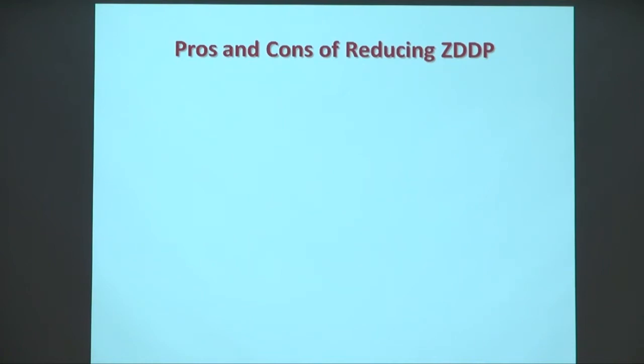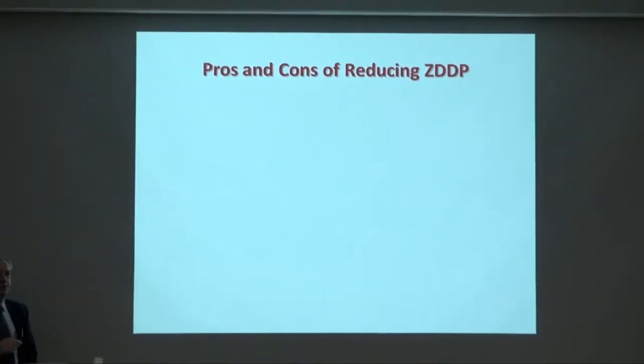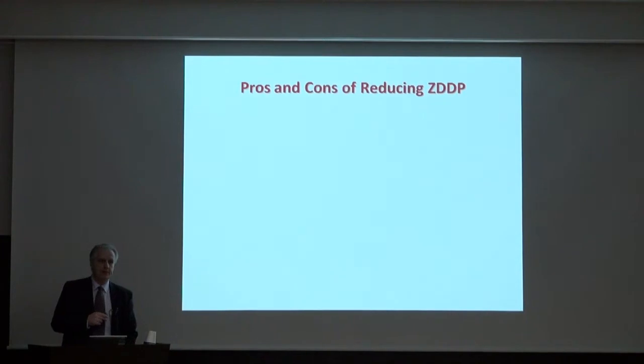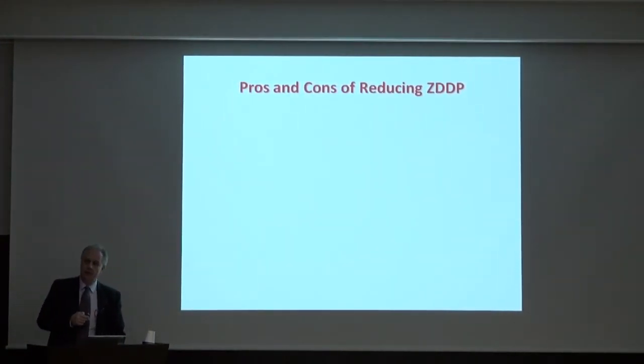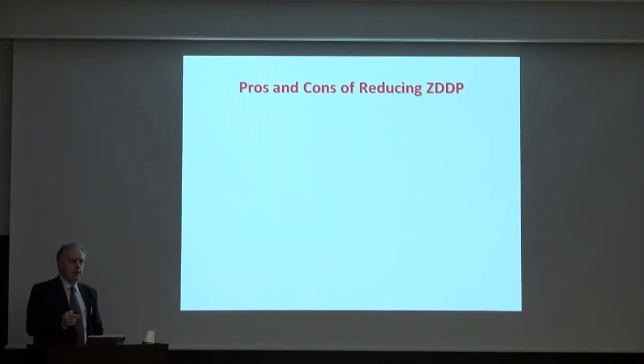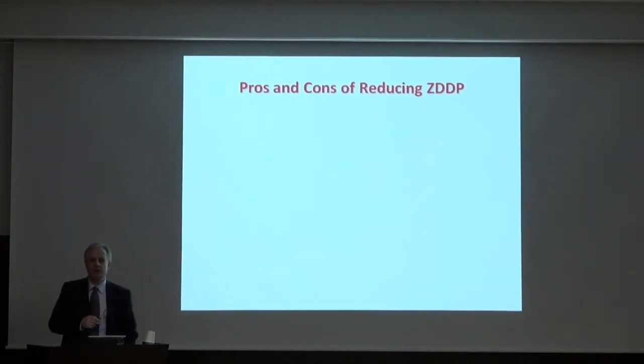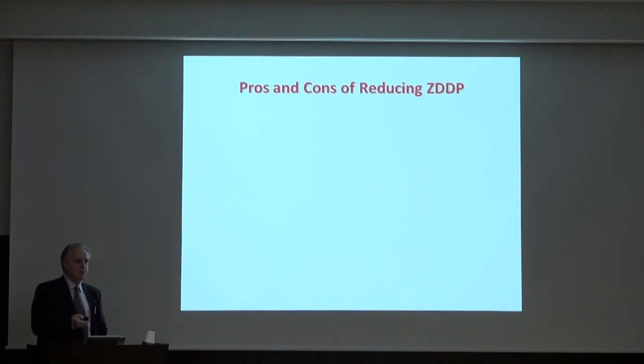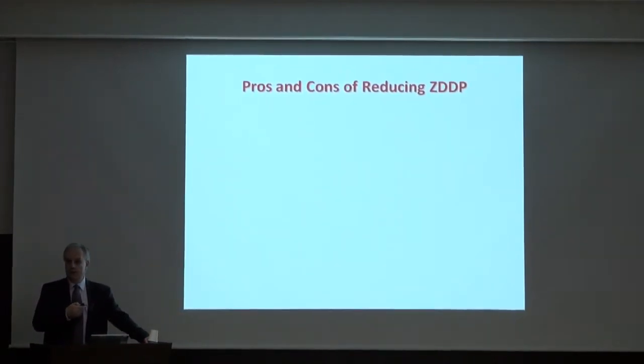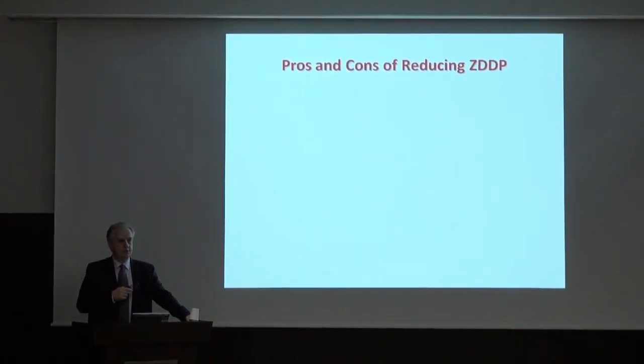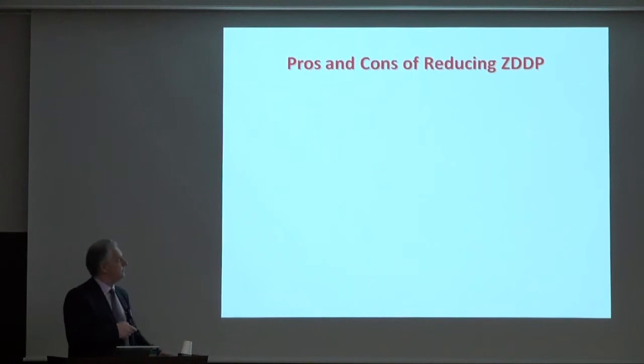This is a long chain molecule that contains phosphorus, zinc, and sulfur, and it's incorporated in the synthetic oils. And today we will learn what its main role is in protecting engine parts by reducing friction, therefore improving the efficiency of the engine, and improving the wear resistance by forming protective tribofilms. I start up front referring to them as tribofilms because they are formed by the rubbing process. Tribo, you see the tribology we said before, and it's therefore a chemistry that is not an equilibrium chemistry. It involves rubbing between the surfaces. The rubbing process activates those surfaces, causing the molecules incorporated into the synthetic oils in these additives to break up, react locally with the surfaces, and form these so-called tribofilms to protect those surfaces.